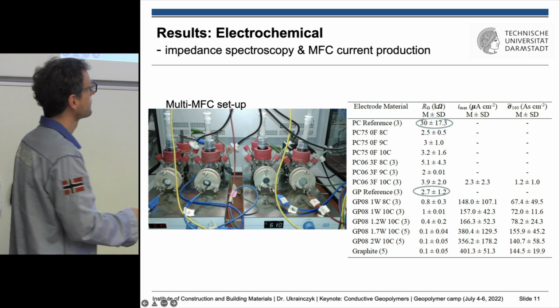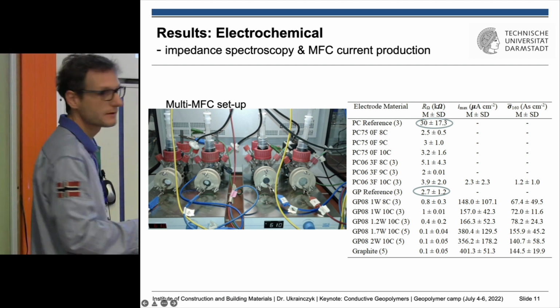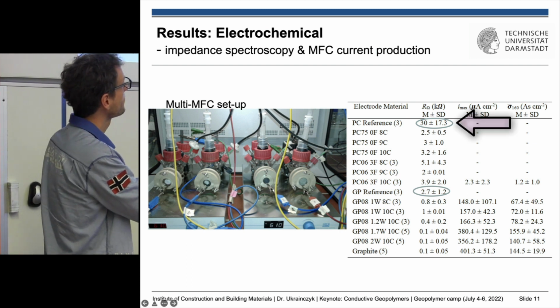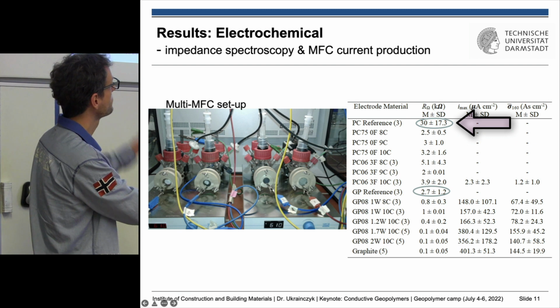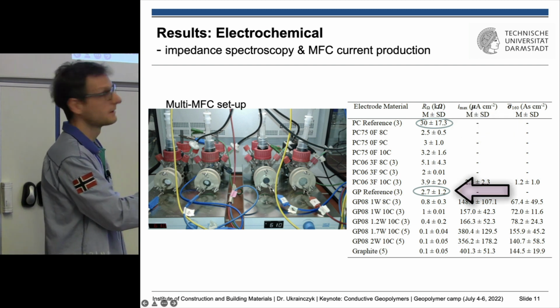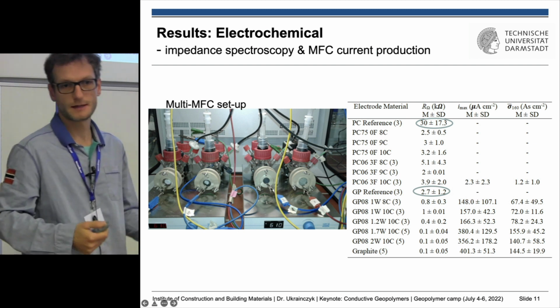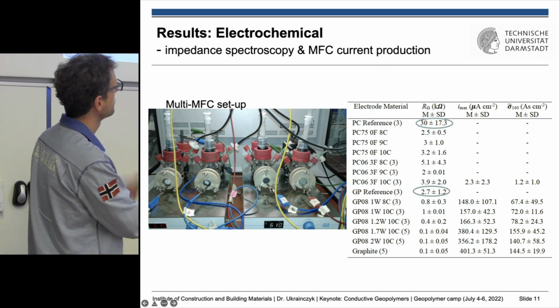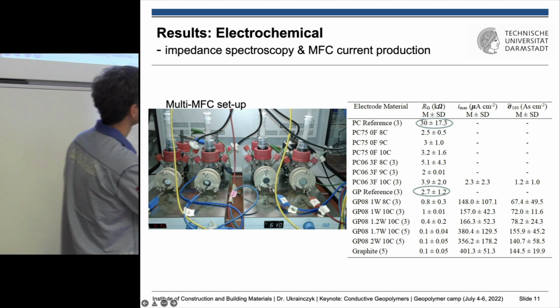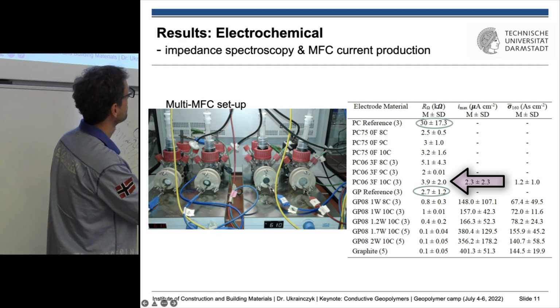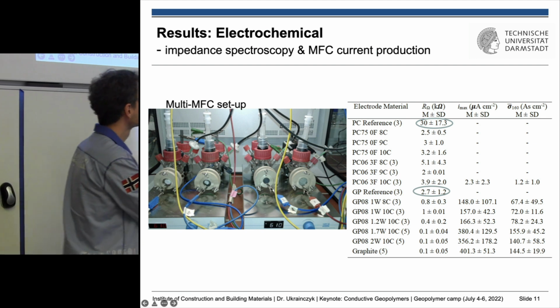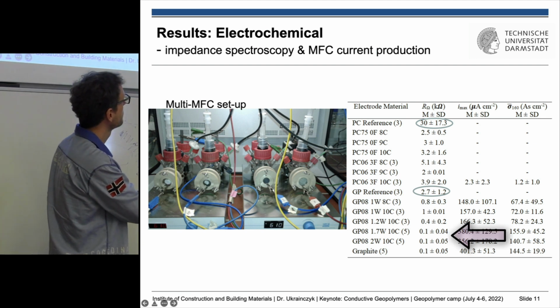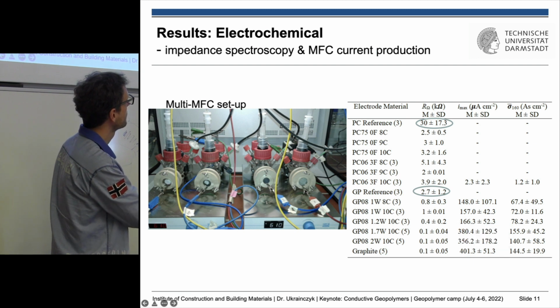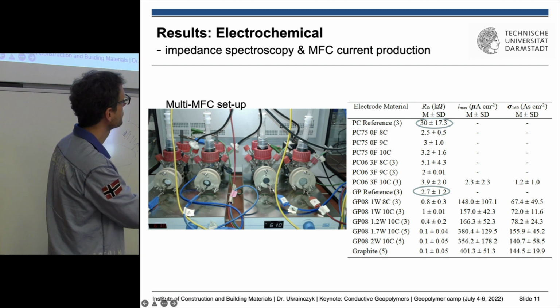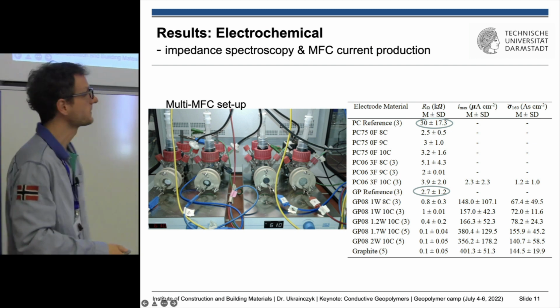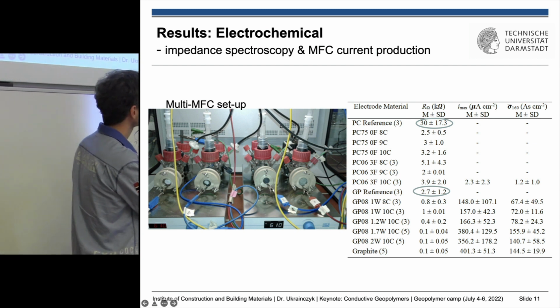And we can see after electrochemical impedance spectroscopy and current production, that for Portland cement the resistance was very high, just for the reference. For geopolymer it was already an order of magnitude lower because of the higher ionic strength. But when we added graphite, we can see that Portland is still quite resistant to electricity. But for geopolymers, we are really reducing the resistivity. And at the end, we get the same resistivity for these kinds of mixtures with water as for the reference graphite.